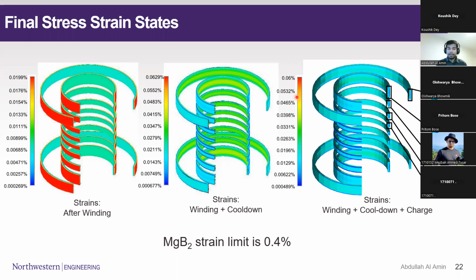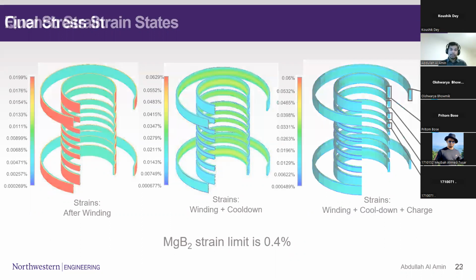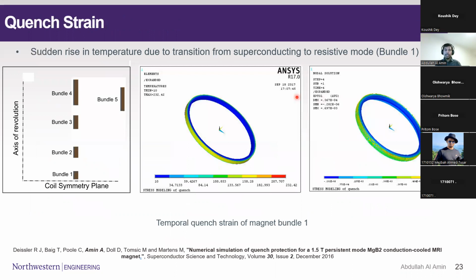If you remember, I discussed briefly the quench process. So this is what is coming next. Quench is a transient phenomenon, meaning that as time goes on, there is a change in the state variable, and we can record that. When a quench occurs, it means that a certain portion heats up. This is very difficult to identify on your screen, but this red spot is basically the increase in temperature. From my simulation, we can see that the temperature has risen up to 232 Kelvin. The corresponding strain, the numbers are difficult to read here, is close to 0.07%.